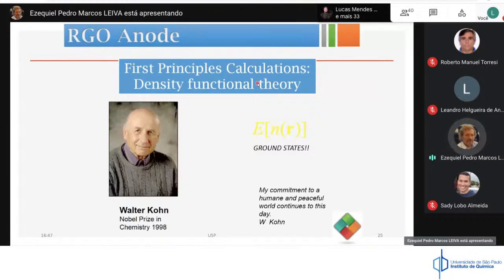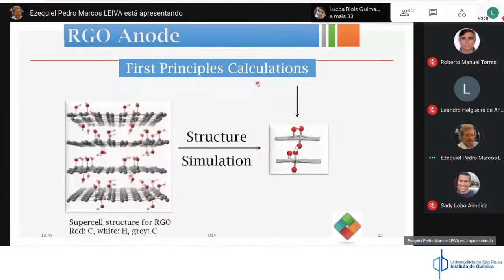And there are a number of programs that can make the calculation for you. Well, in our case, I will give some examples of how we estimated the insertion potential of lithium into a reduced graphene oxide anode. Reduced graphene oxide is graphene oxide which has been modified by some oxidized species and further a bit reduced. So you can now estimate or consider different structures and analyze what the insertion potential of lithium is in this structure. You can predict the electrode potential you expect to have with this system.